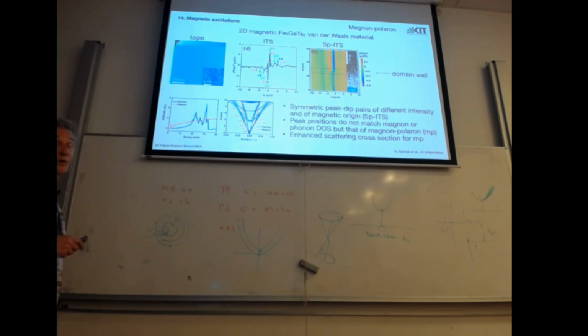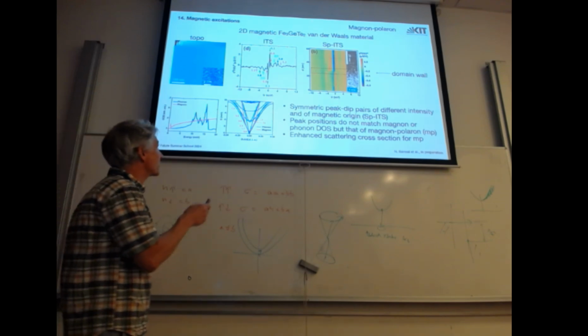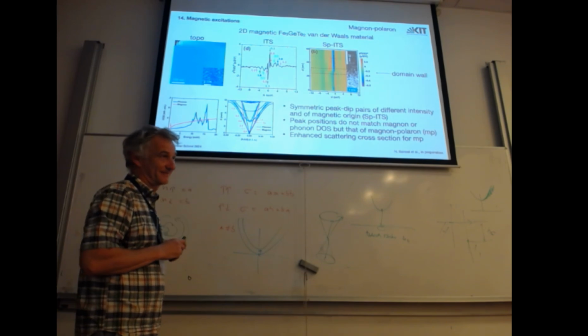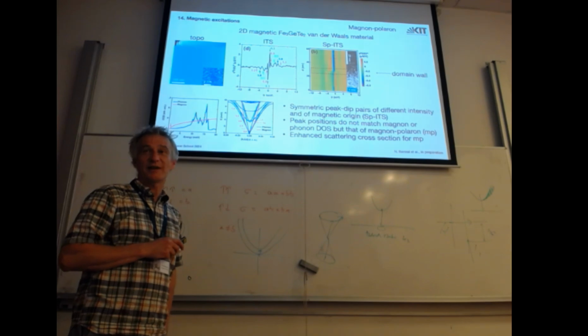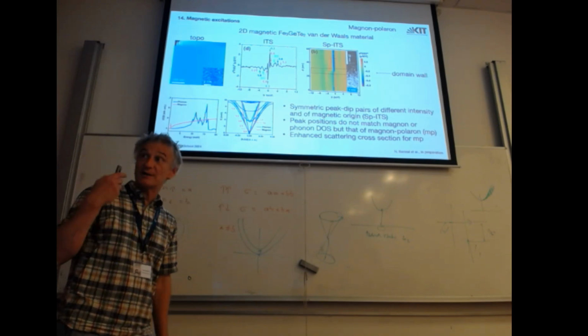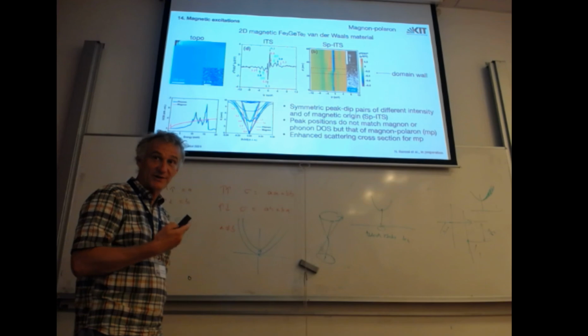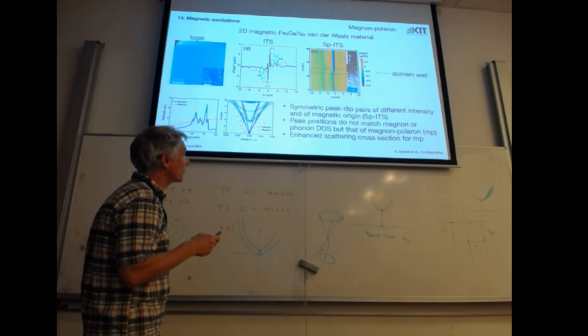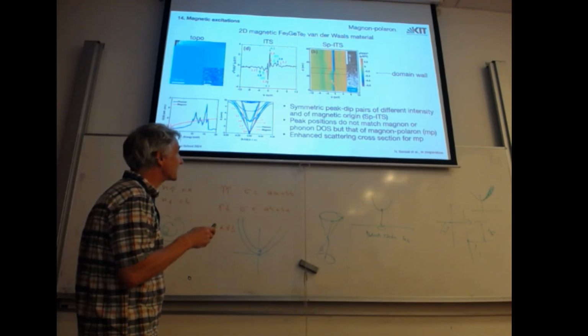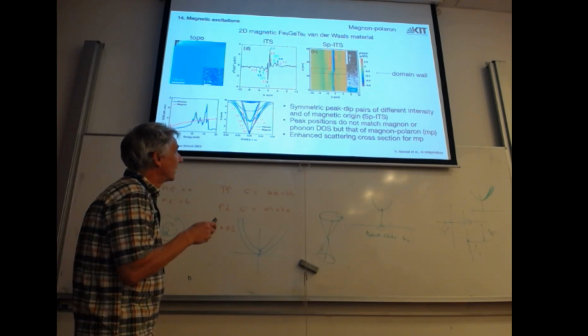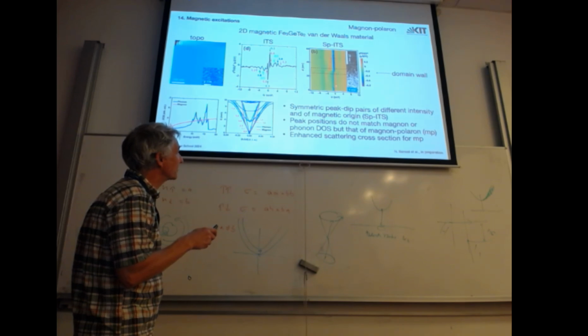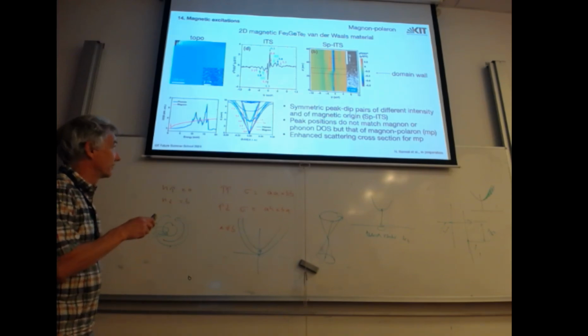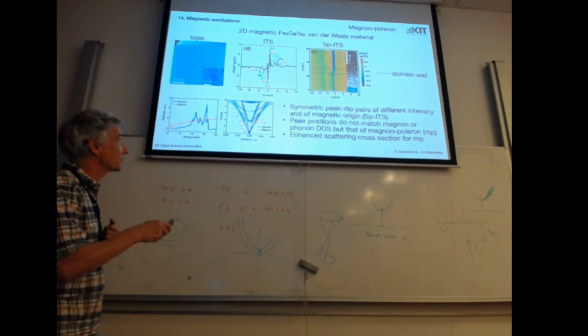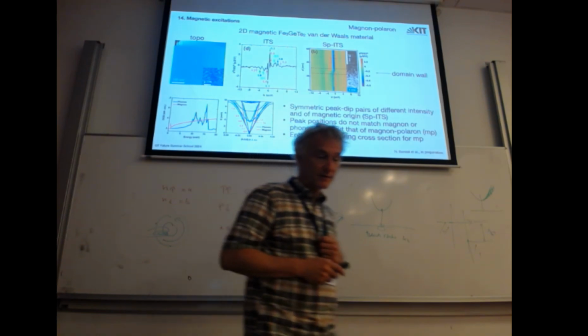We can see magnetic domain walls in this material taking a spin polarized tip. We can measure this inelastic tunneling spectroscopy spin polarized. So if this is a phonon, it doesn't care about the spin of the electron. If this is a magnon, we expect a change of the intensity of these inelastic processes. And that's exactly what we see. So this is a domain here. So this is position, and this is energy, and I color code this. So red means high intensity, blue means low intensity. And you see these peaks here. For example, this one changes in intensity when we go to the domain wall, and this one also. So all of the peaks actually change. These must be magnetic peaks, since they change the intensity when you go across the magnetic domain wall. So we know whatever excitation this is, it is of magnetic origin.